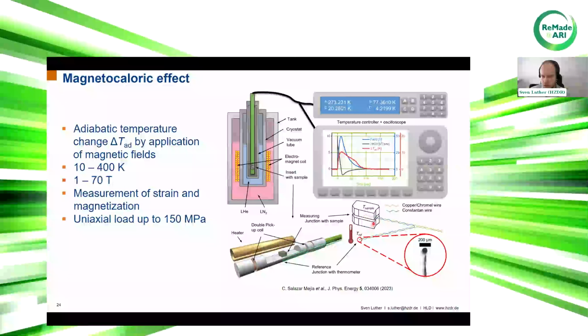The sample preparation is a sandwich type, where in between the sandwich we have our thermocouple to measure the temperature change, which is coupled to a temperature reference outside of the sample, which is usually a Cernox thermometer. The reference temperature is recorded on a temperature controller, and the change of the sample temperature and also our external field from the pickup coils is recorded on an oscilloscope. In red, you can see the voltage over time on the oscilloscope, which is the change of the temperature over time. From the external field, we usually record dH/dt, the change of the field over time, in black. By integrating this over time, we get in blue our typical pulse field shape, field over time.